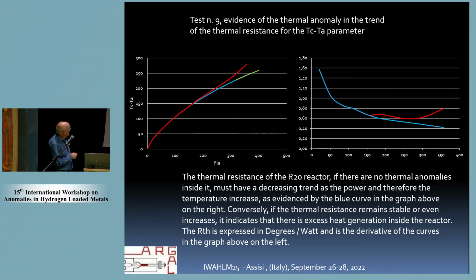You can see clearly here that the slope of the curve goes in the good direction for us. It means extra heat, and it is confirmed by the behavior of the thermal resistance: if there is no extra heat, it should go down continuously, while if you have stability or an increase of thermal resistance, it means that inside the reactor something happens in terms of extra energy.